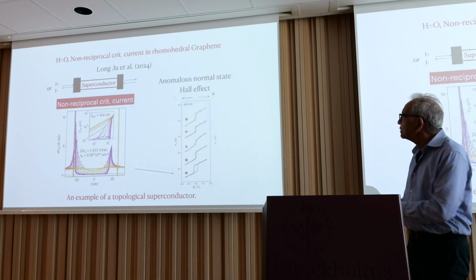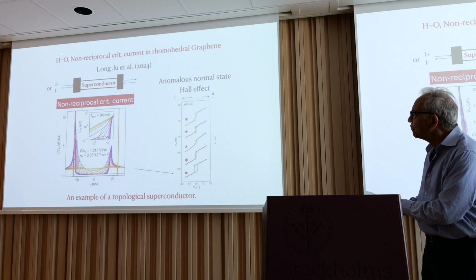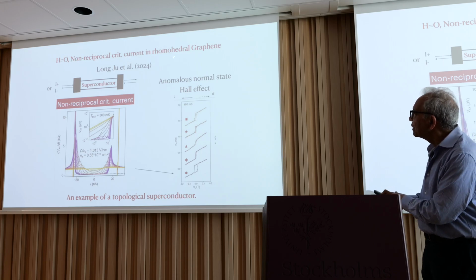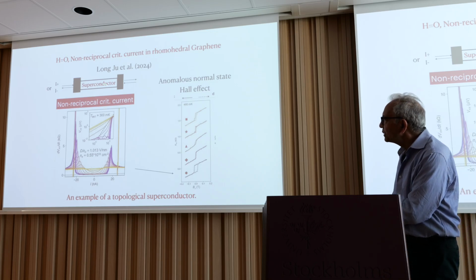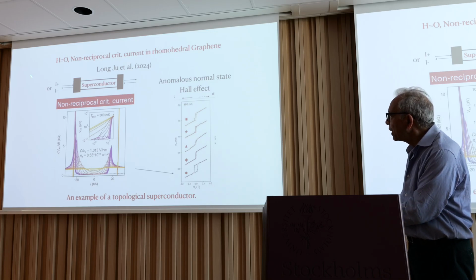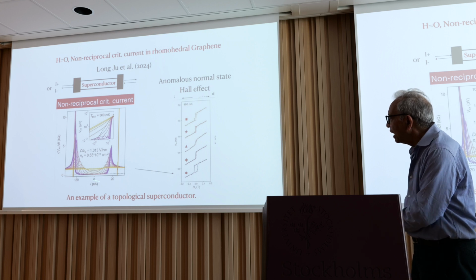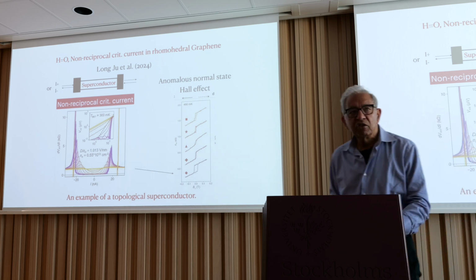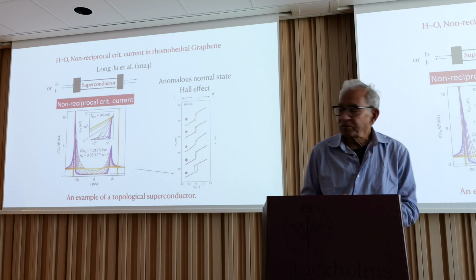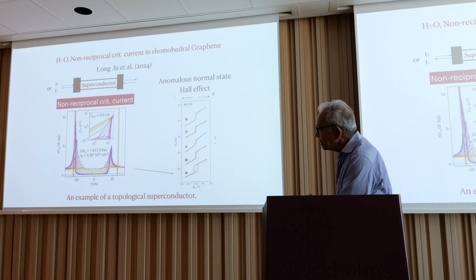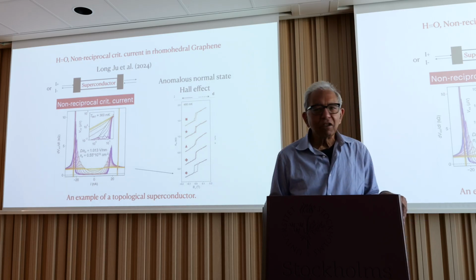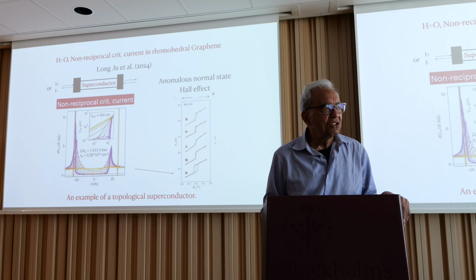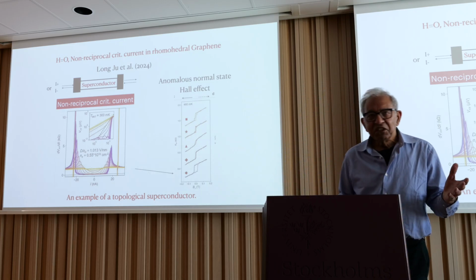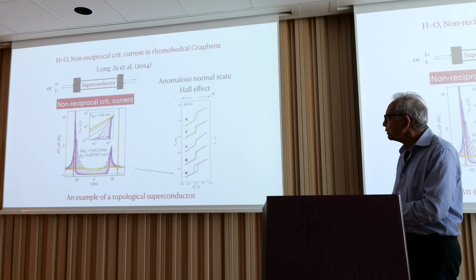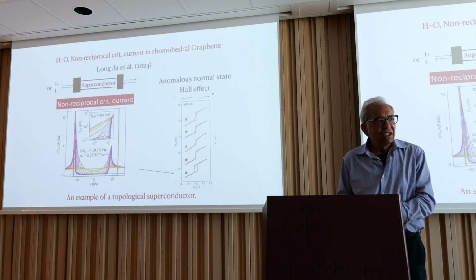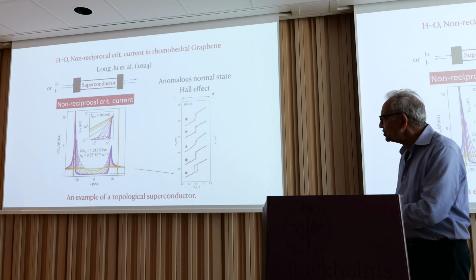So let me first talk about a clearest example of the zero field non-reciprocal critical current. So you take this superconductor and you pass a current in this direction, and you observe when you begin to develop a finite voltage. And then you pass the current in the opposite direction, and you observe when the sample begins to develop a finite resistance. In principle, a very simple experiment. In practice, I'm told it's not easy to get the conditions exactly right.